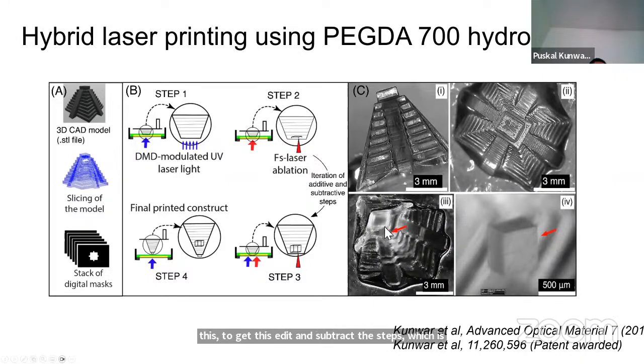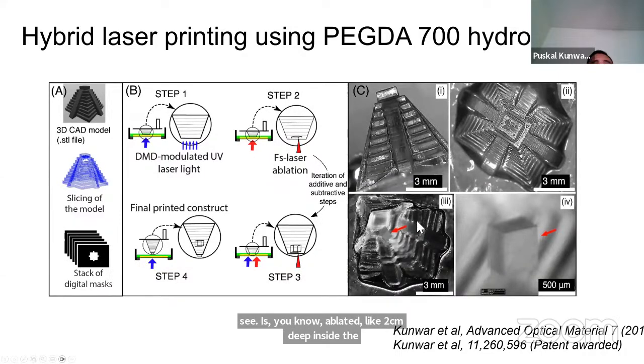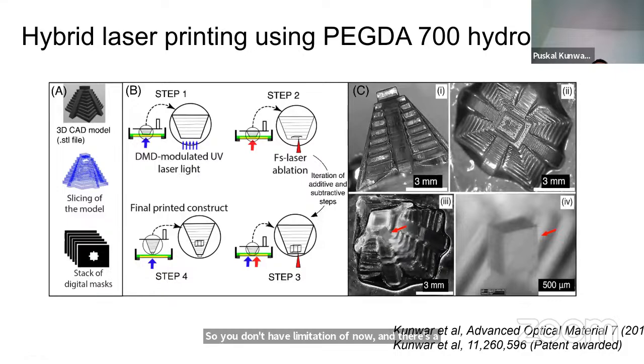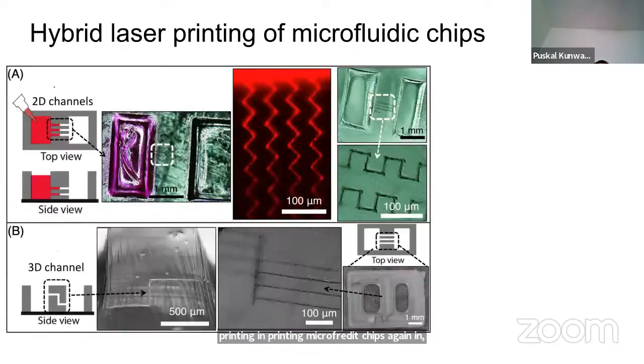These cubes you see here are ablated 2 centimeters deep inside the structure, so you don't have the limitation of laser penetration in ablation using this technique. This was done in model PEGDA 700 hydrogels. We have mostly used this hybrid laser printing to print microfluidic chips, again in PEGDA 700, which is not biodegradable, but not biotoxic. It's a biologically inert material.